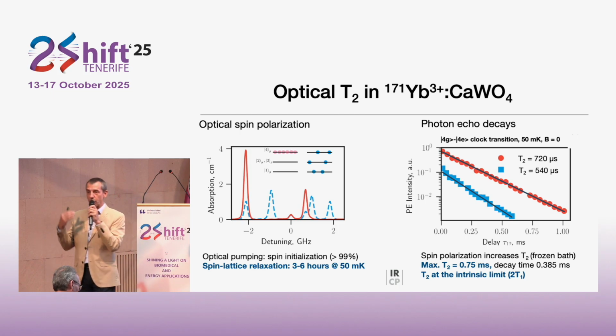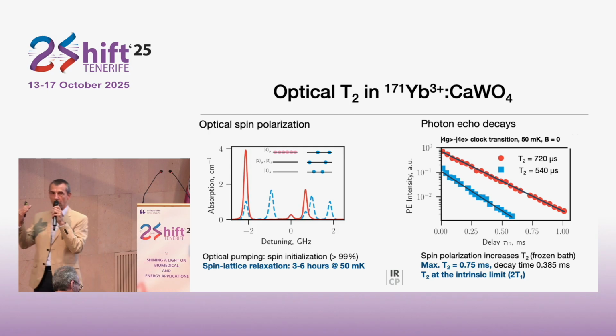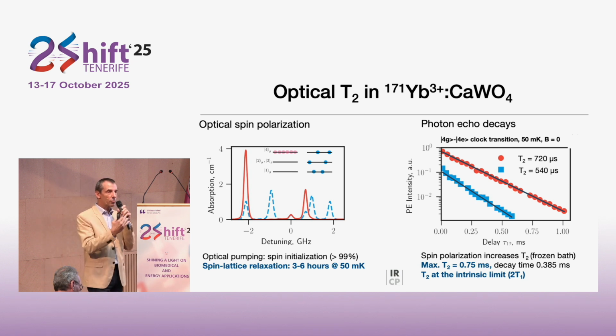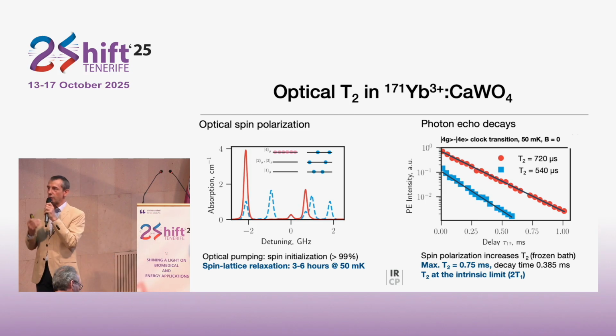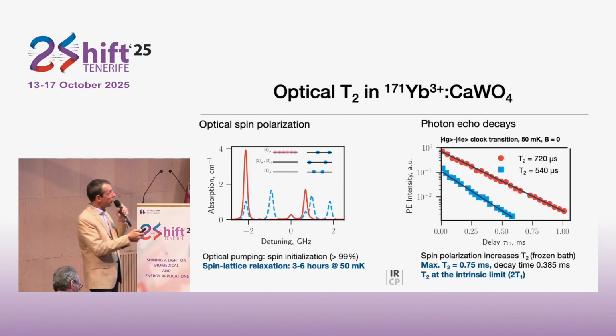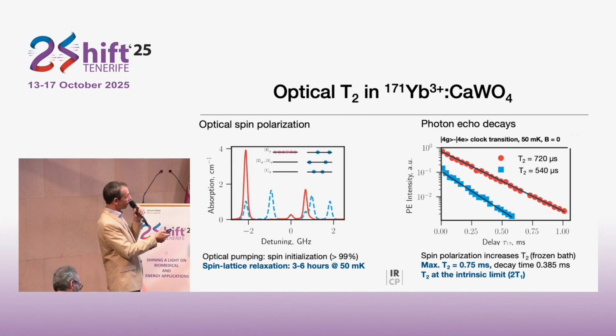It's simply because when we polarize the spins in the same level, we actually freeze their dynamics. So with the frozen dynamics, the noise which is produced by the spin is reduced, and so the perturbation to the ytterbium transition is also reduced, and we see an increase of the lifetime of the quantum state. So we have a situation of a frozen bath.